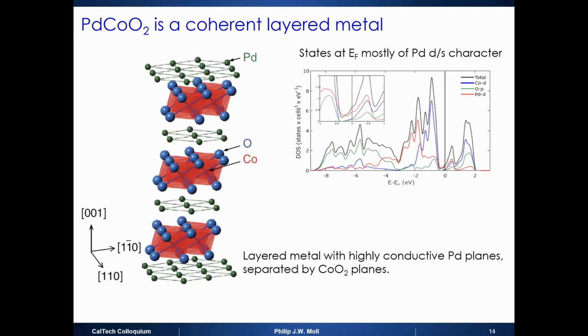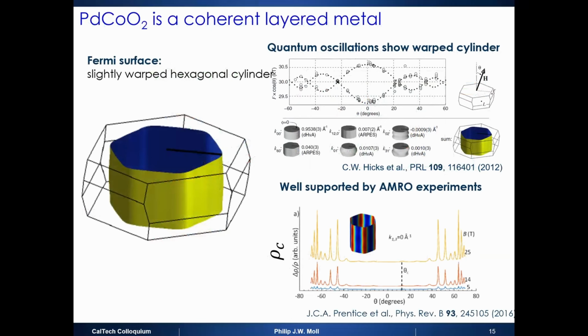because that's at the end of the day what we're doing things for. So there's a large stream of research in the group going on palladium cobaltate. This is one of these delafossite materials, and you can think about this as essentially hexagonal planes of palladium that are separated by cobalt oxide. So it's a highly two-dimensional conductor, and its Fermi surface, or the electrons at the Fermi level, entirely come from these palladium atoms. That's where the conduction comes from. By and large, you can think about this as hexagonal palladium sheets that are weakly coupled. And not surprisingly, in such a 2D system, you find a Fermi surface that is almost perfectly two-dimensional. It has a nice twist to it, namely that its cross-section area is almost a mathematically perfect hexagon. So it's very, very hexagonal, not round.